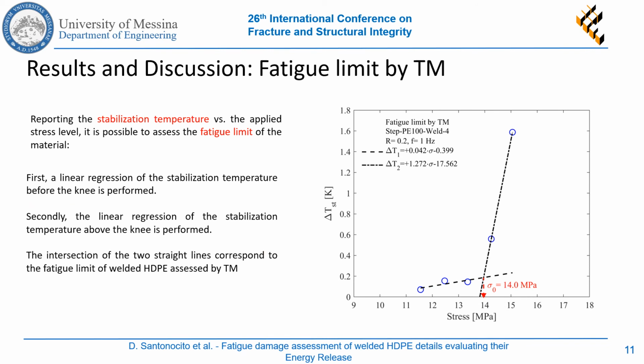If we report the different stabilization temperatures versus the applied stress level, it is possible to observe two linear trends with different slope. The first linear trend is typical of stress levels below the fatigue limit of the material and can be ascribed to noise in the temperature signal or material damping, while the second is characteristic of energy release due to fatigue damage phenomena. By the intersection of the two linear trends, it is possible to assess in a very rapid way, even with one specimen, the fatigue limit of the material.